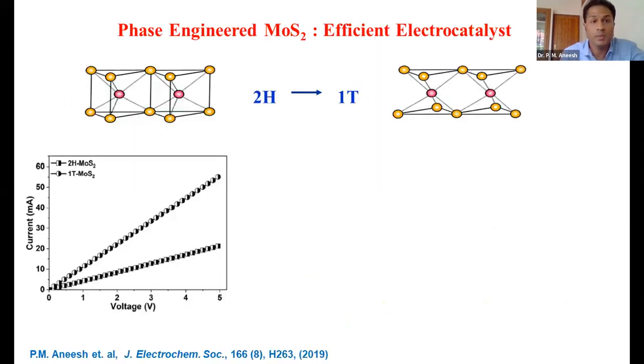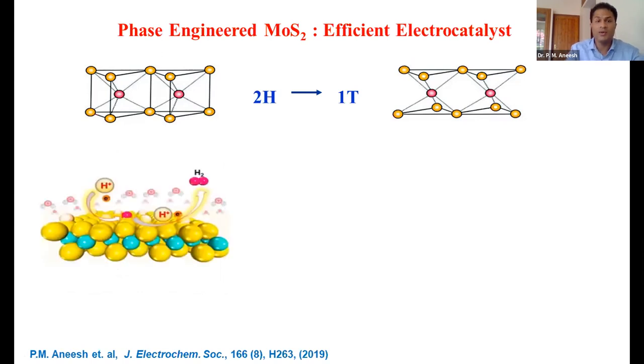And another thing, as I mentioned in the initial slide, there are two types of material. One is the hexagonal system and another one is the tetragonal system. One is a semiconductor and another one is a metallic system. So we have fabricated or synthesized the two types of system by changing the conditions of the hydrothermal synthesis. And we got improved conductivity for the 1T MoS2, that actually tells you the 1T system is more conductive.